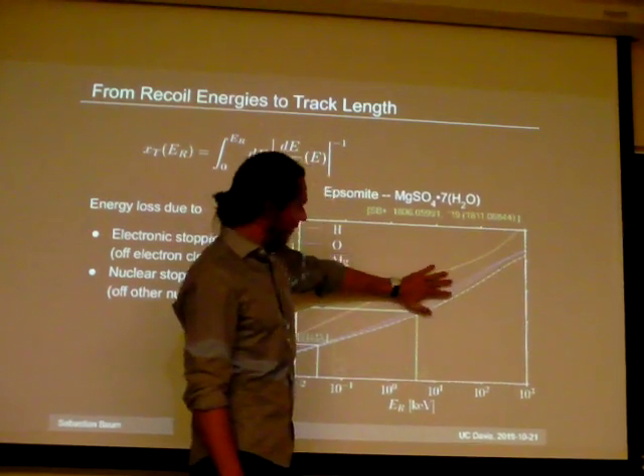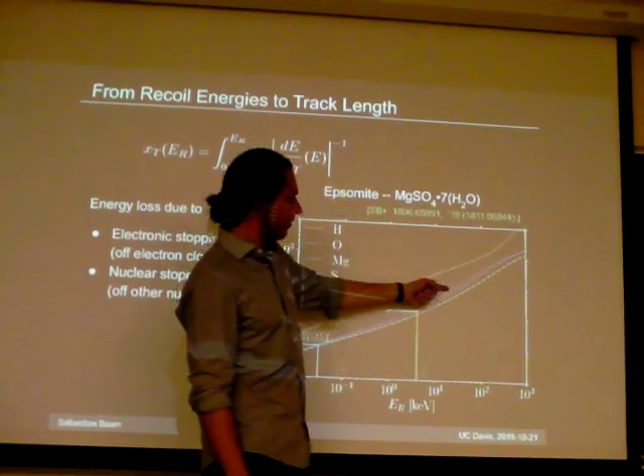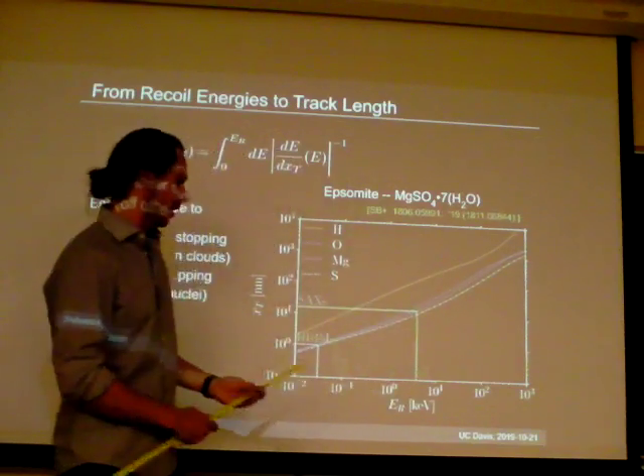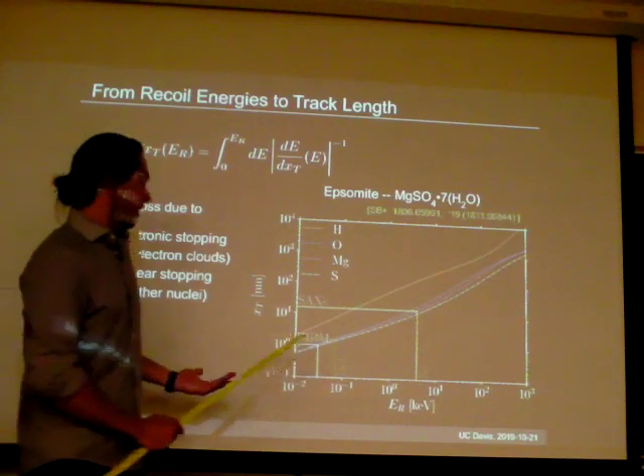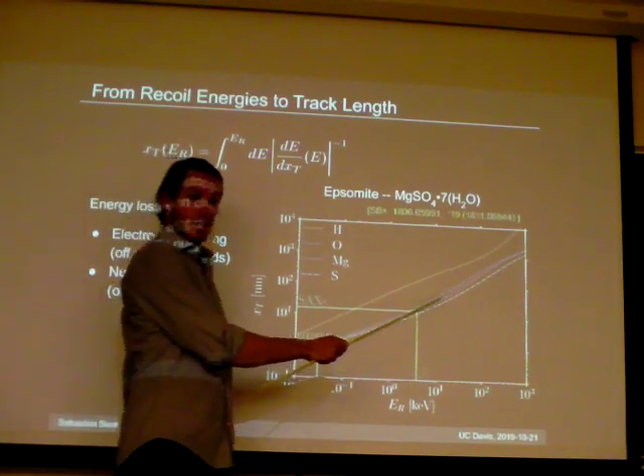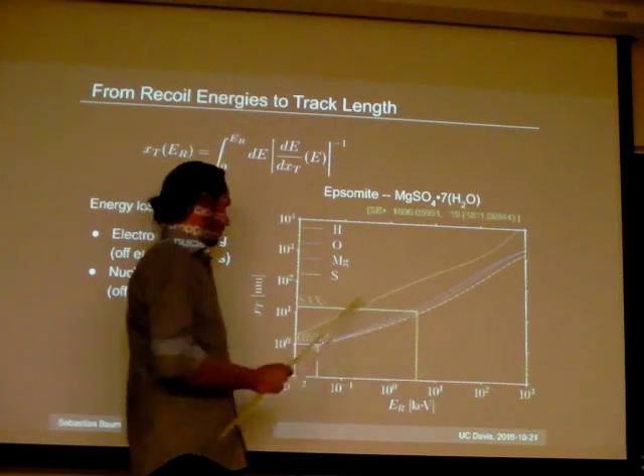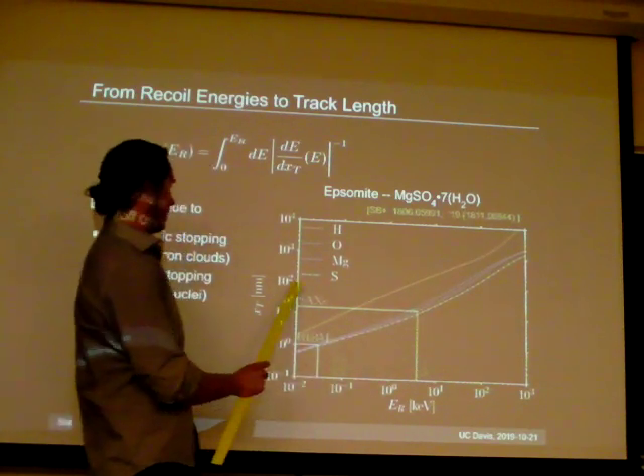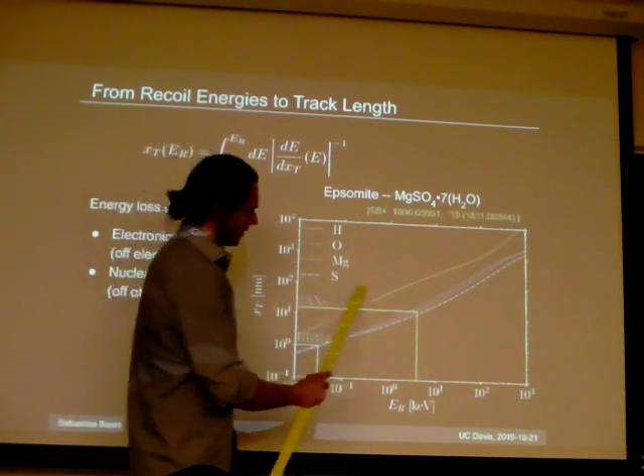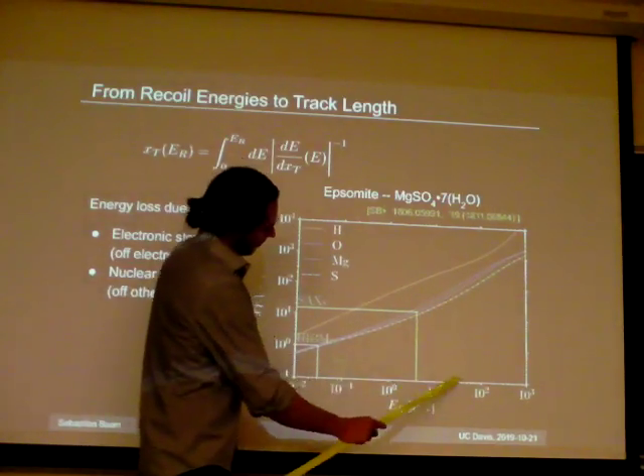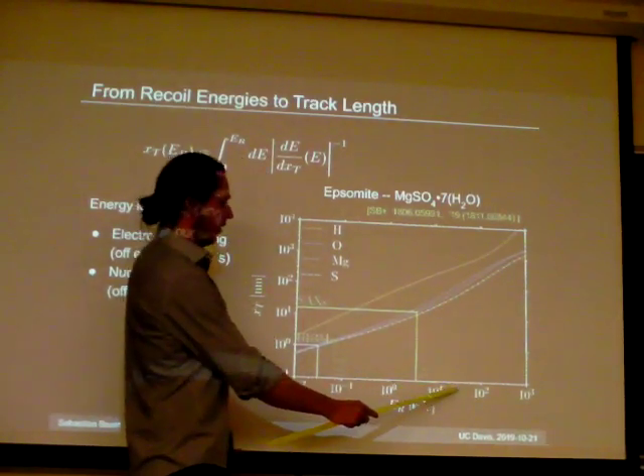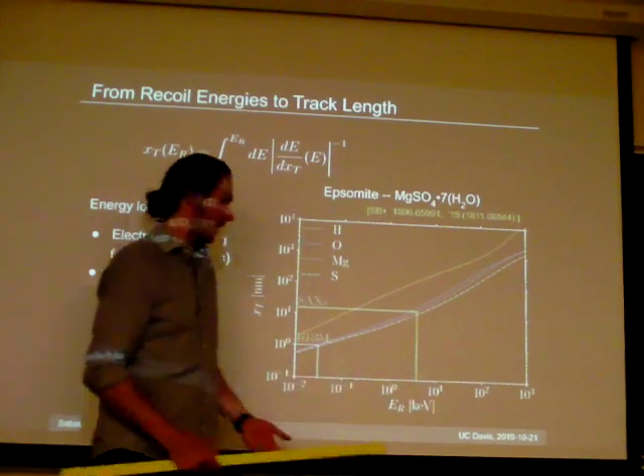And you see the track lengths from these are relatively similar. For each particular mineral you have a one-to-one relation of a recoil energy and a track length. But in reality, once you see a track, you're not going to be able to say what it actually came from out of this. So you're just going to be able to see, look, I measure a track of say 100 nanometers. Okay, it's going to correspond to a recoil of, in this case, something like 25 keV or so, right?